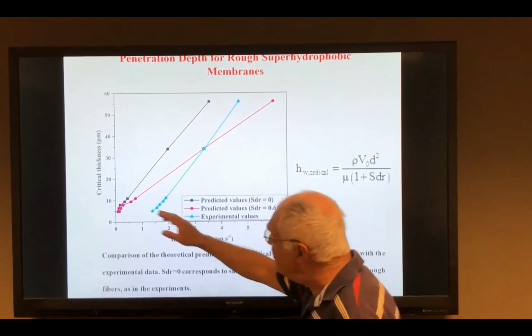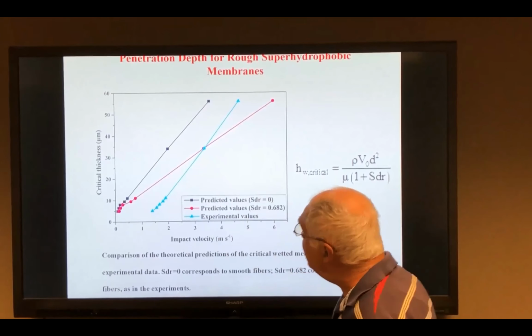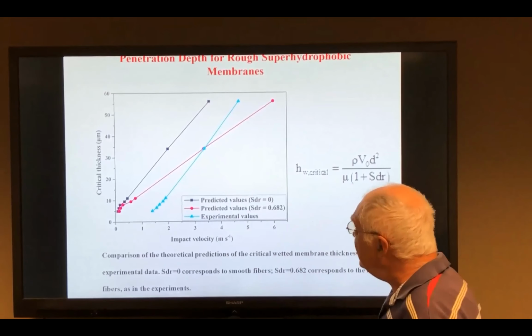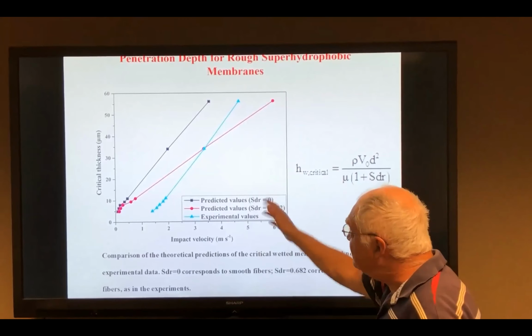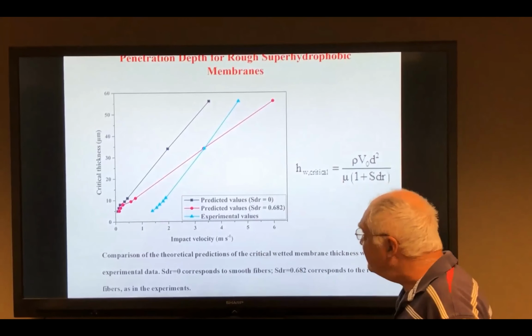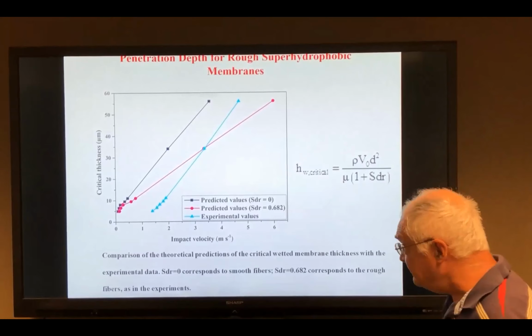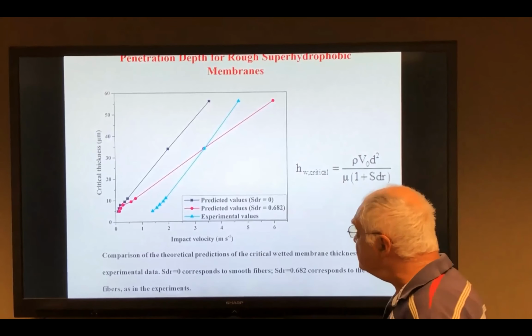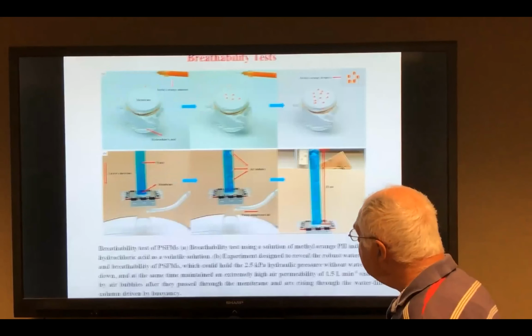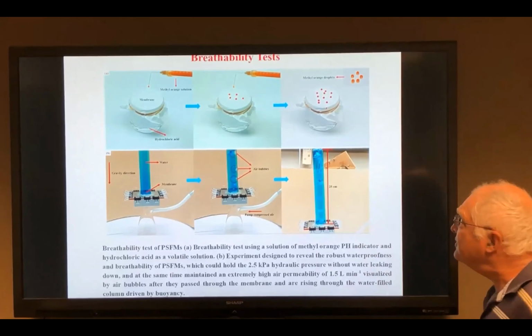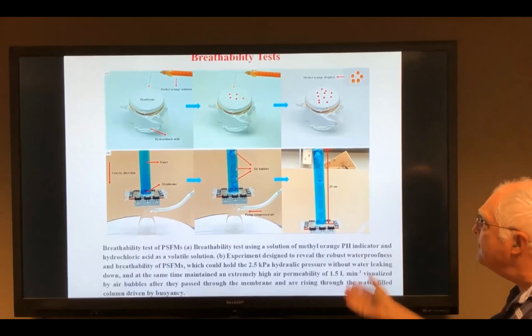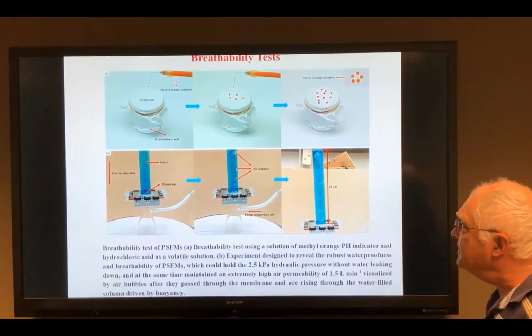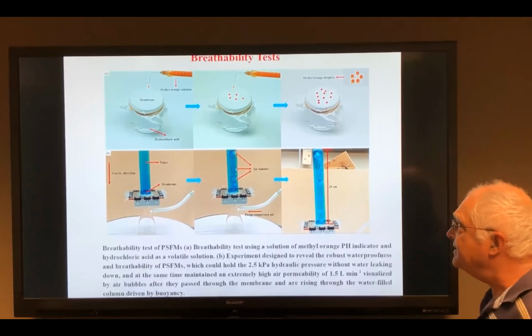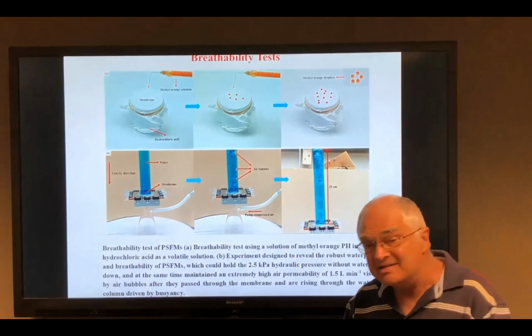You see that when you go from about 10 to about 50 micron thickness, you can prevent penetration up to about 5 meters per second, which is of interest for water droplets. The next slide, please. Just in brief, these membranes should not only be impenetrable for water, but they should also be penetrable for gas, breathable.